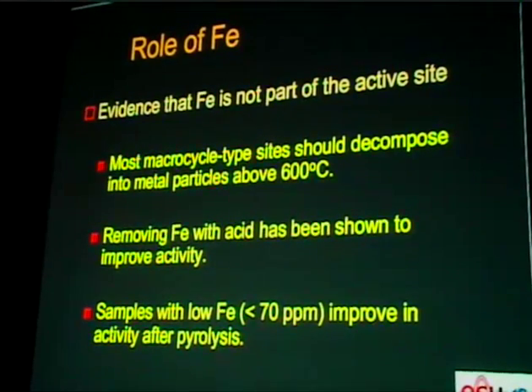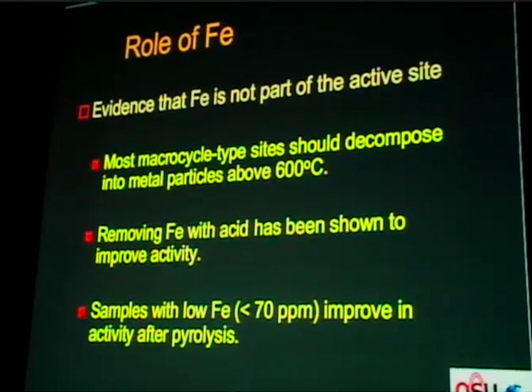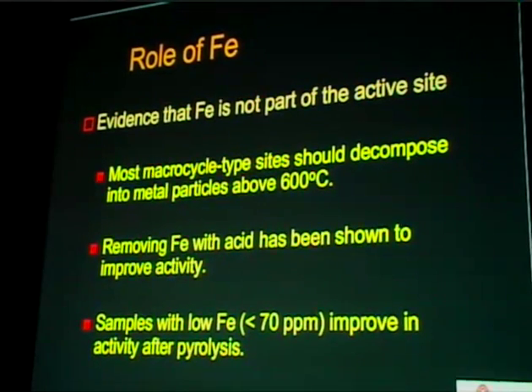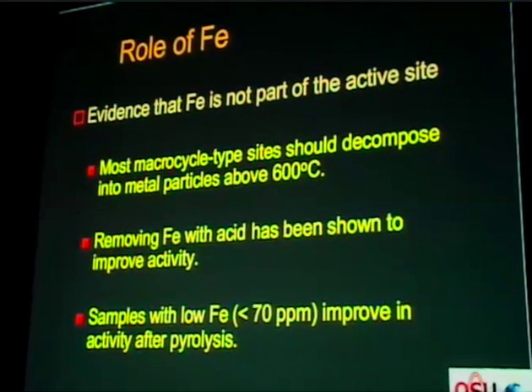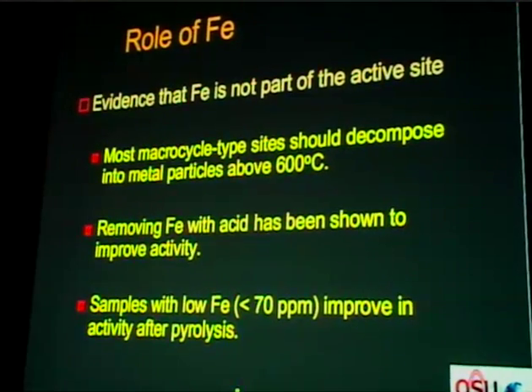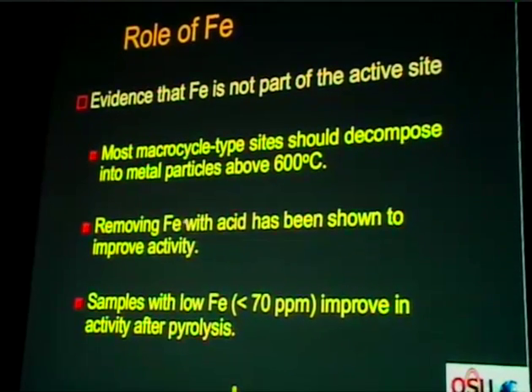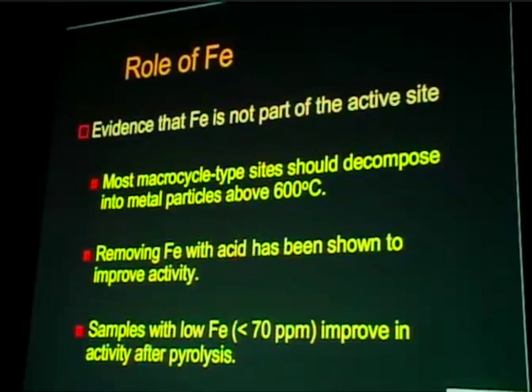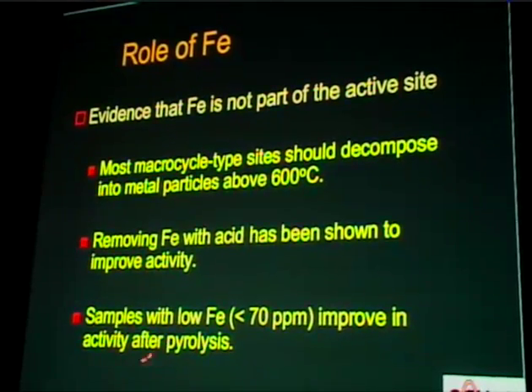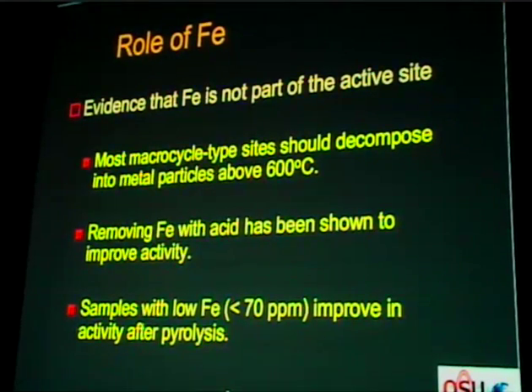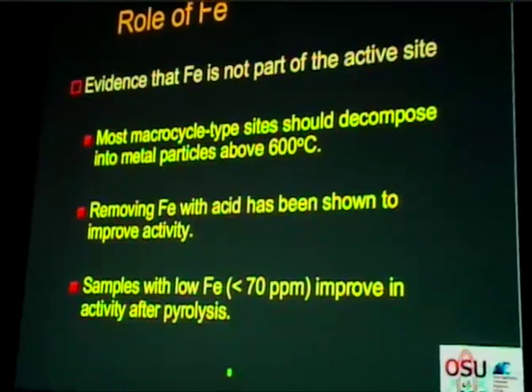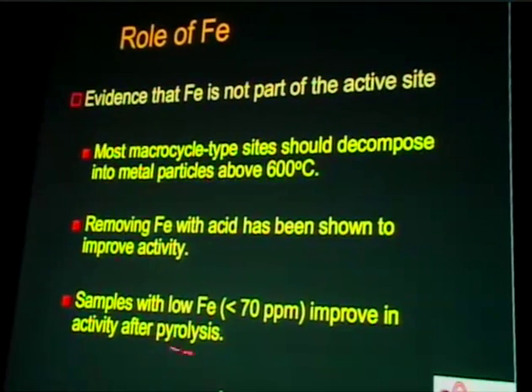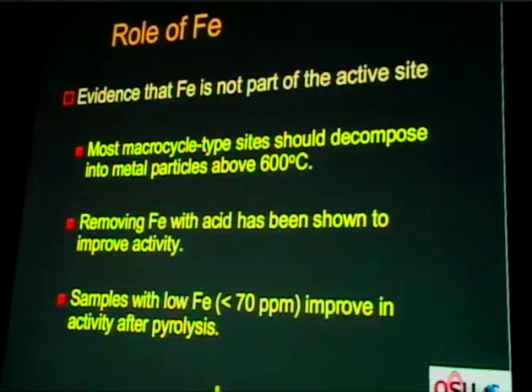The fact that most macrocycle type sites should decompose into metal particles when they are treated above 600 degrees centigrade. It has also been shown that if we remove iron, actually we may improve activity, and samples with very, very low iron concentrations can still show activity after some pyrolysis treatments.